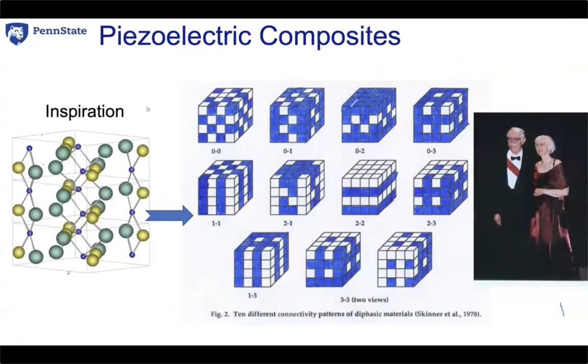The one he probably told the most often, however, was that he looked at the crystal structure of antimony sulfoiodide, which is a chain structure ferroelectric, where the connectivity between one chain and the next chain is very weak. As a result, this material has a very large anisotropy in d33 versus d31. And so Professor Newnham looked at that and said, I can do this artificially by making piezoelectric composites.